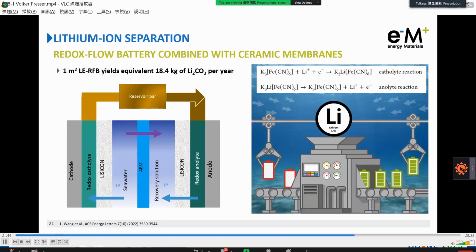Earlier, I briefly mentioned the redox flow battery system that Professor Junsu Kim and us explored for lithium-ion recovery. In that setup, we used a pair of two LISICON, lithium superionic conductor electrodes, ceramic, that separated the redox catholyte and the redox anolyte. We also had to separate the seawater from the recovery solution, with a simple polymer-based anion exchange membrane, AEM. The anion exchange membrane allowed not the lithium, but the chloride ions to move from the seawater into the recovery solution.